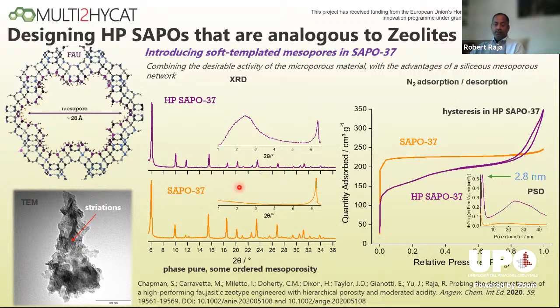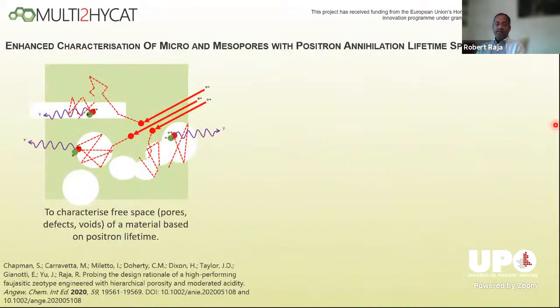One can then also do nitrogen adsorption studies, again conventional studies, and you see the microporous material really has no mesopores, whereas the hierarchical variant now has this typical hysteresis loop, which confirms the presence of these mesopores. But one of the fundamental questions which still arises is how interconnected are these micropores and mesopores? And in order to look at that, we used some enhanced characterization methods. So here is a technique known as positron annihilation lifetime spectroscopy, or PALS for short, where we use positrons to bombard the micropores and mesopores of your catalyst.